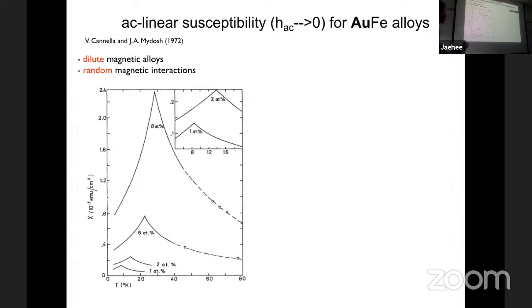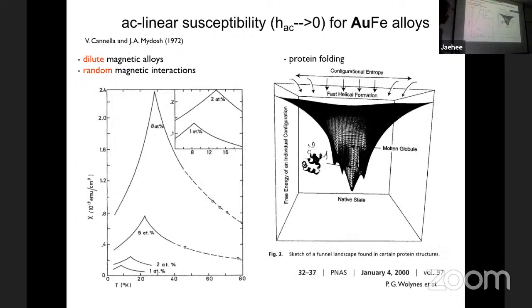So let me just show you. If you have this kind of funnel type energy landscape, then if you cool down, it goes around here, and then when you warm up the temperature, you access this excited state. That's why it goes up here. But now, instead of zero field cool, if you do field cooling at base temperature, and then crank up, instead of this, you stay here. I'll show you a little later, but the field cooled and zero field cooled hysteresis is the hallmark of the glassy state. What kind of state the system accesses at low temperature depends on the external magnetic field, and is very sensitive.